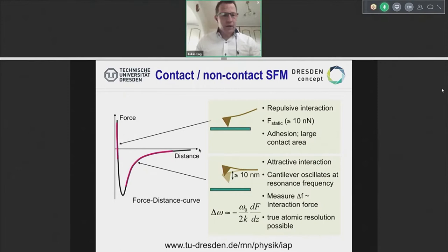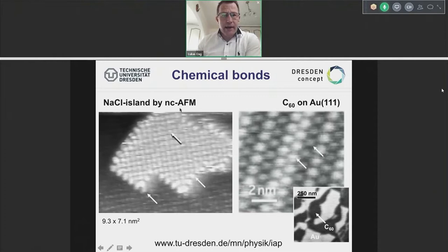Here are the two examples. First, we see a sodium chloride island that has been measured in Basel with non-contact atomic force microscopy. You see the atoms of one single sodium chloride island. Let's focus first on the center here. You can see from this atom, marked with an arrow, that we have a circumference of one atom to the top, one to the right, one to the bottom, and one to the left, and exactly one also in the next layer below. In other words, if you count the so-called coordination number, this atom has a five-fold coordination. Now let's move from this atom to the rim, this atom here.